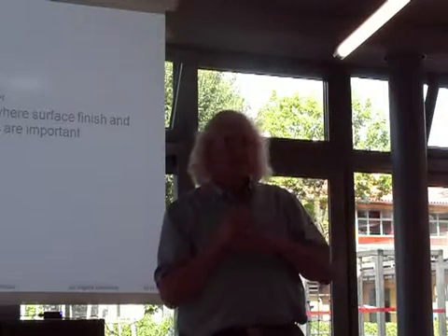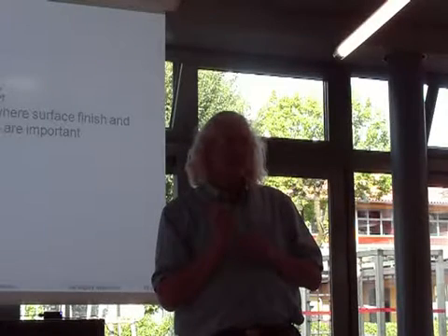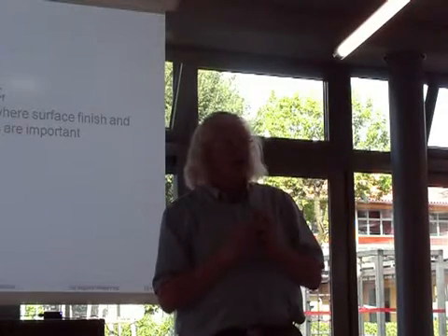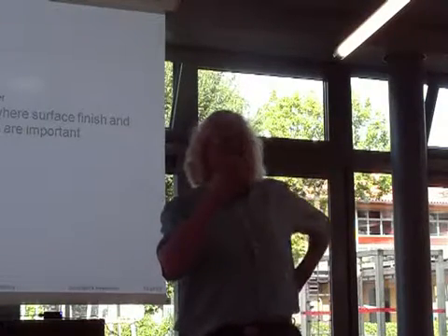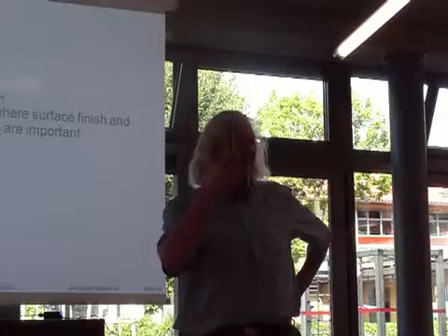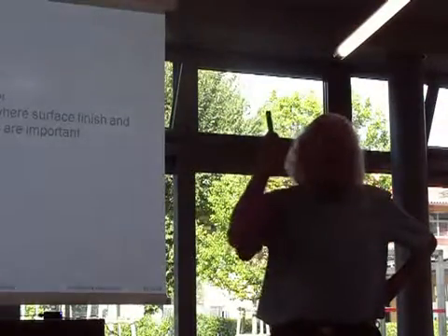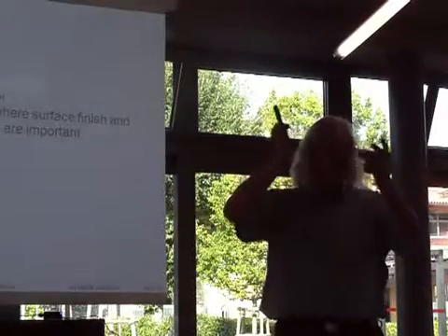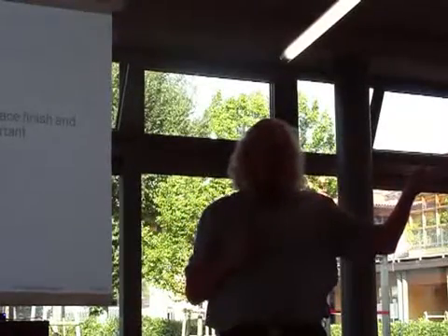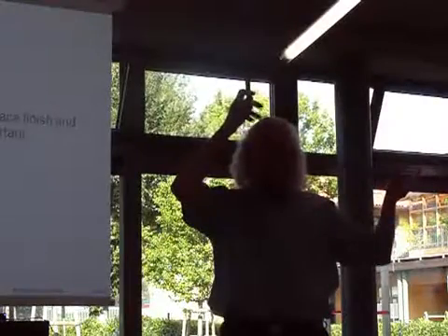Well, that's a true statement, but the process doesn't work. Why doesn't the process work? Well, the process doesn't work because all the material behavior comes from testing in a situation where plasticity dominates everything. And everything is based on material behavior having the right physics. So if I test in a region dominated by plasticity, and yet at very long lives, the failures are governed by the microstructure. Microstructure is more important than plasticity.